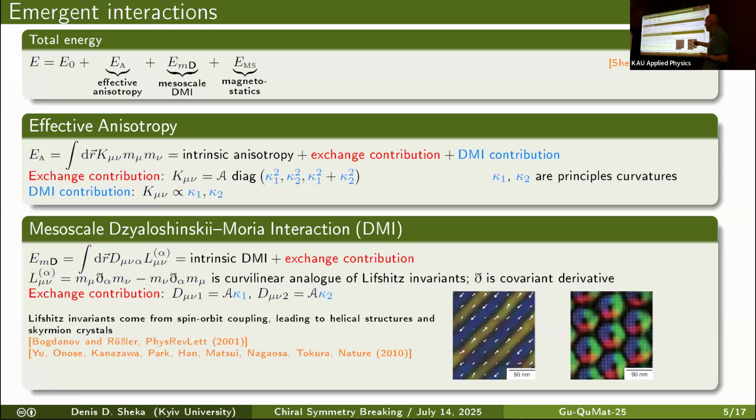In this case, they are typically quadratic in curvature, and they can come from Dzyaloshinskii-Moriya interaction. Here, the effective anisotropy is linear in curvature. But finally, we have the biaxial anisotropy, and geometrical effects are determined by two principal curvatures in the case of a film, or curvature and torsion in the case of a wire.